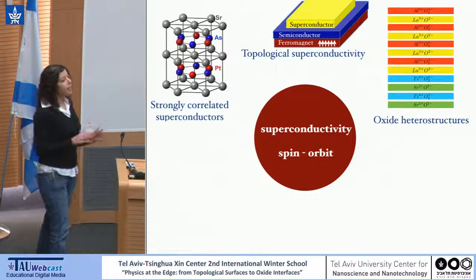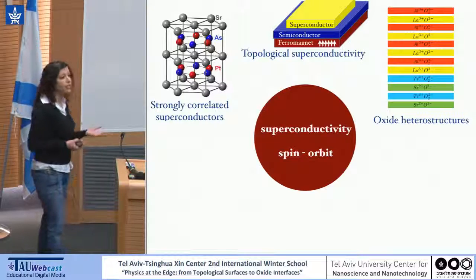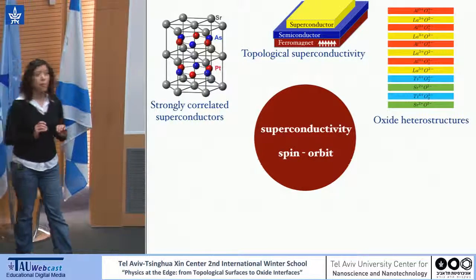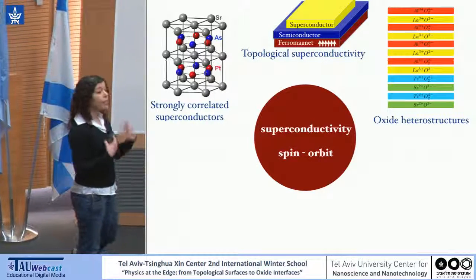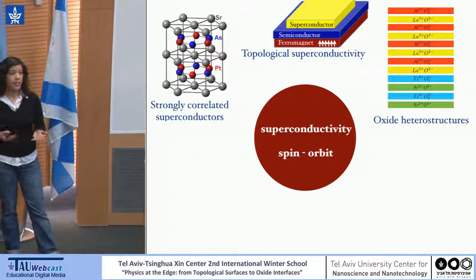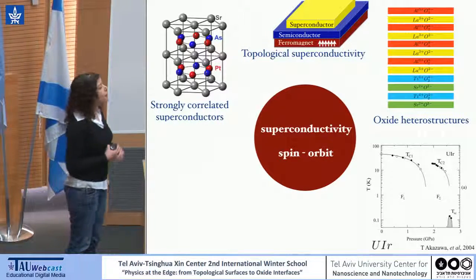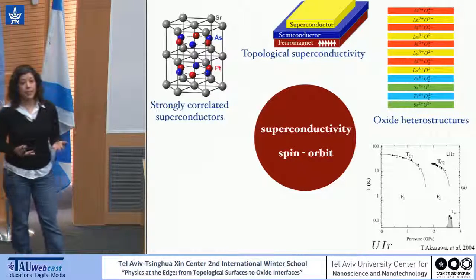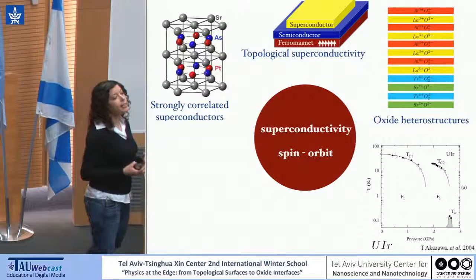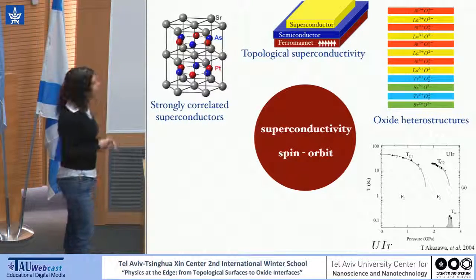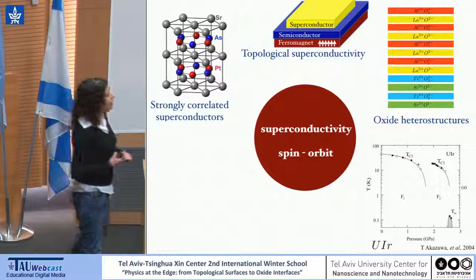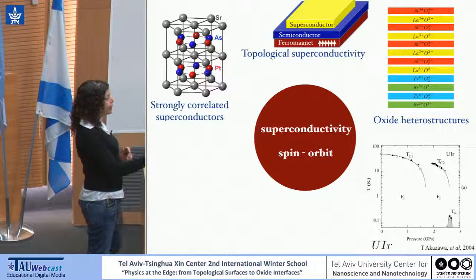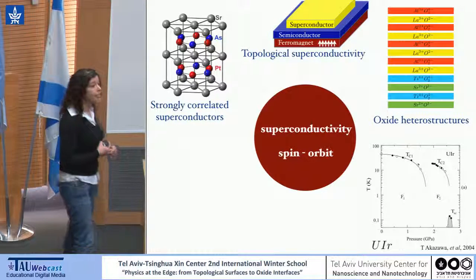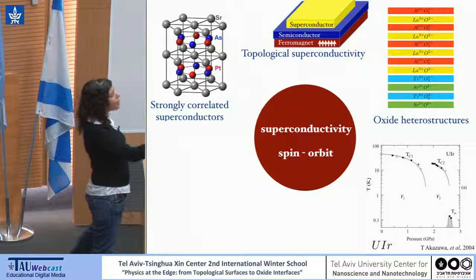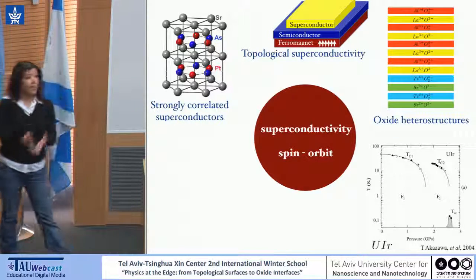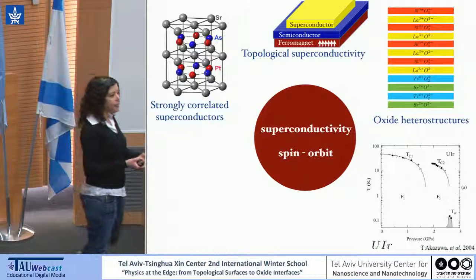Now, there are many effects that are coming because of the interplay between superconductivity and spin-orbit coupling, but I'm going to focus on one part of that, and that is the effect of either external magnetic field or internal magnetization. And we know now of more and more materials where superconductivity in the presence of spin-orbit coupling appears in the vicinity of magnetic transition. So here, for example, it's uranium iridide, UIr,, where upon applying pressure, they can see that they have 2 transitions between 2 ferromagnetic states, strong and weak ferromagnetic state, and at the end, they see superconductivity.